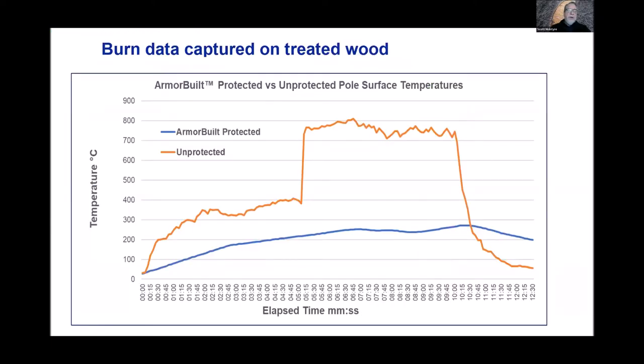And then this graph basically shows it's in Celsius, but really what it demonstrates in the blue line is the protected material and the red line is the unprotected. And when you see the red line jump up there at around 5 minutes, that's where the three impinged gas burners come on in the 10-minute test. So it jumps up quite high right there. And the protected material, that's why you can see the efficacy of armor belt with regards to how well it protects the wood.